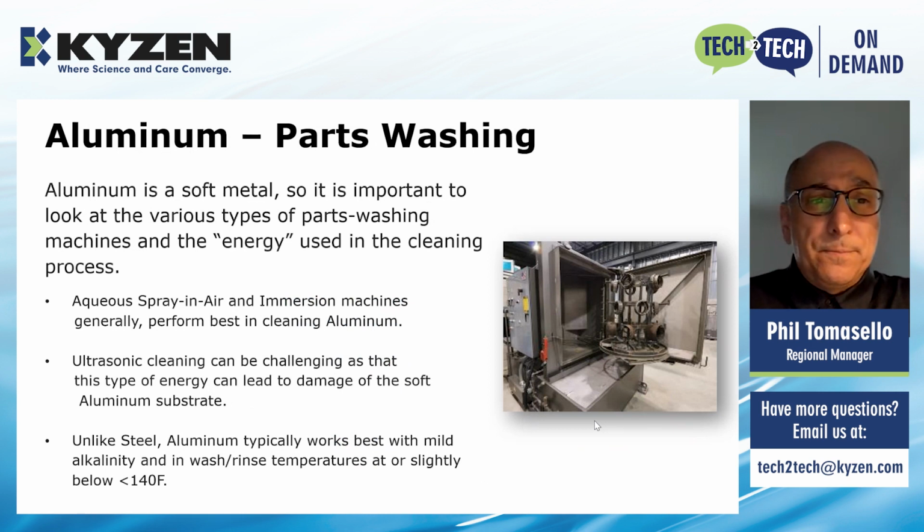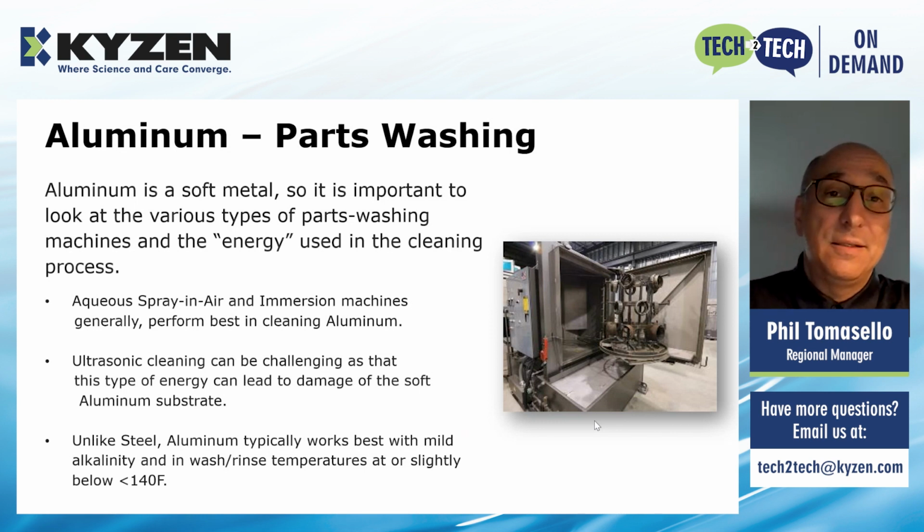Talking about aluminum, we know it's a soft metal, so it's important that we look at parts washing machines, and we look at the specific energy used in the cleaning process. Spray in air and immersion are two processes that KYZEN believes perform the best in cleaning aluminum. Ultrasonics can certainly be used in the aqueous process. Just keep in mind that aluminum's soft, so it could damage the substrate. Unlike steel, aluminum typically works best if you keep those temperatures below 140 degrees. And if people are washing above 140 degrees Fahrenheit, you can actually see yellowing of that aluminum. So, important considerations when you're looking to clean aluminum.